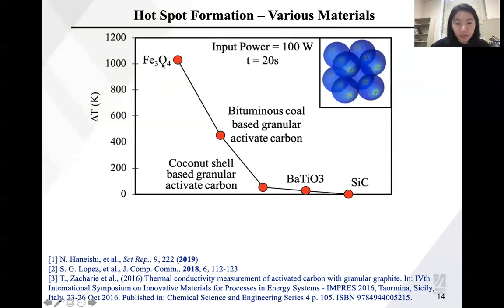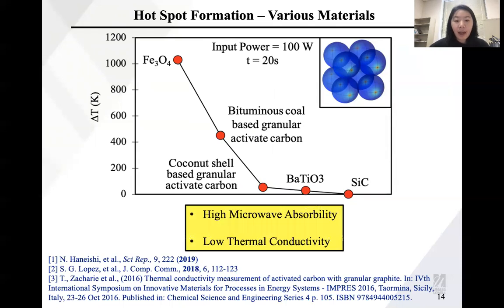Then with this conclusion, we tried more materials for hotspot formation, including iron oxide, activated carbon, perovskite, and silicon carbide. What we found is that when a material has high microwave absorbability and low thermal conductivity, that material can lead to a significant hotspot. But when you have really high thermal conductivity, even though your microwave absorbability is high, the hotspot won't form, because as soon as the hotspot forms, it will distribute the temperature to the rest area of your catalyst. So silicon carbide doesn't have hotspot formation.